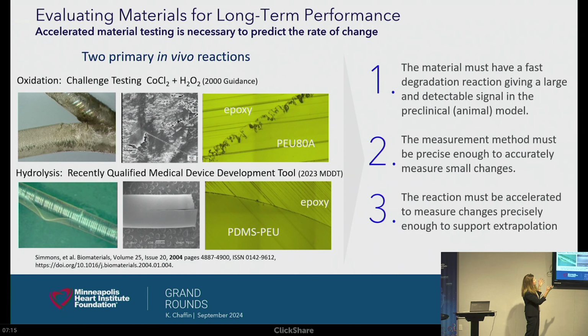So when you look at these reactions and you think about how you're going to predict long times, there's really only 3 ways to do it. The first way is the material can react super fast. You can see it in that ISO standard 1-year assessment. It's 60 days at 70 degrees or 1 year in the body, but we don't want a material that reacts that fast to create a 50-year lead. So that's not going to work for us.